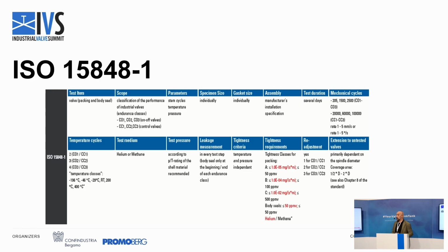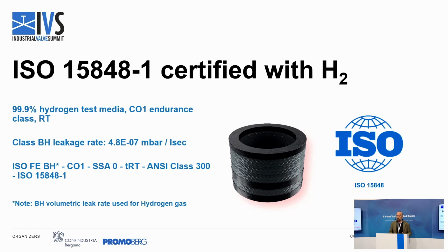We discovered that at least for the non-static position, such as the valve stem, hydrogen does not behave at the same level of helium. So it's not enough to test the valve with helium. We can achieve fugitive emission performances with this kind of product.